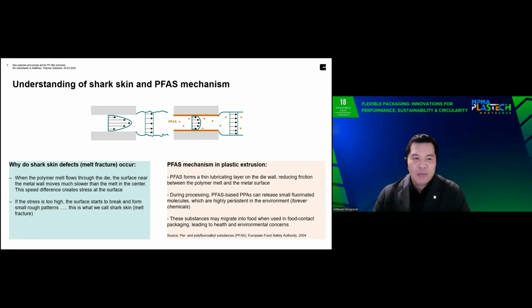You can see from the left-hand side photo that when polymer melt passes through the die, there's a velocity profile difference between the center and the edge, because the surface friction of the metal part also plays a role in creating that difference. When the velocity profile difference is too great as it comes out through the die, it generates stress, and when that stress is too high, it generates shark skin.